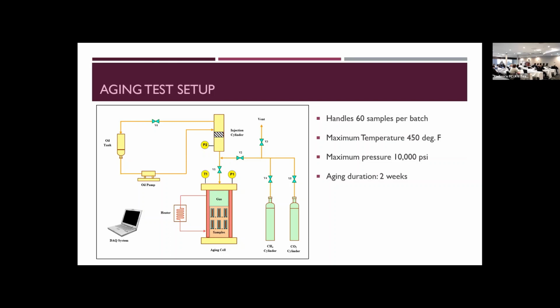I have seen some papers, not with carbon dioxide, but just neat cement, and as a function of temperature, the shear bond strength increases up to 200 degrees C, and then it starts reducing. So in this study, I'm struggling with whether the CO2 is actually strengthening it, or is it just the temperature which is strengthening it?